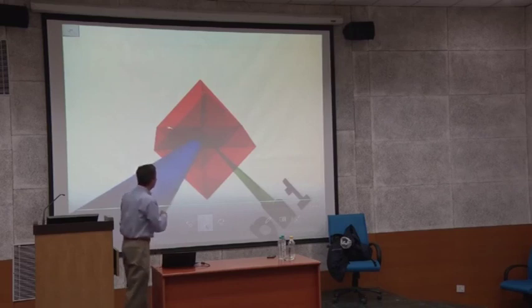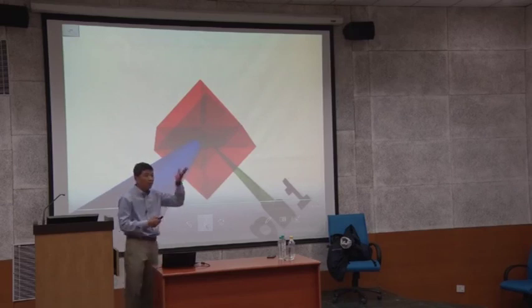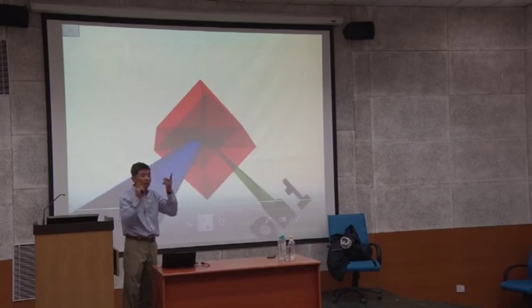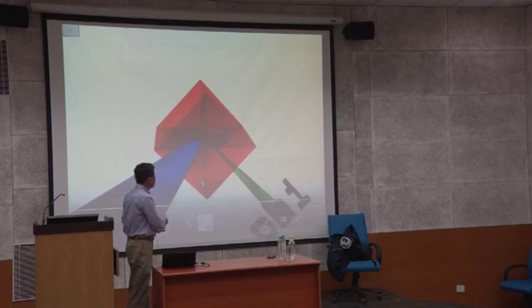You have this plane. How many of these? One here, one there. You have multiple inside. I draw only 4 because of the 101 planes, a family of 4 of them. And when you rotate this phi, every 90 degrees of phi, it meets the diffraction condition. It comes out here. It's very hard to draw these things in 3 dimensions.